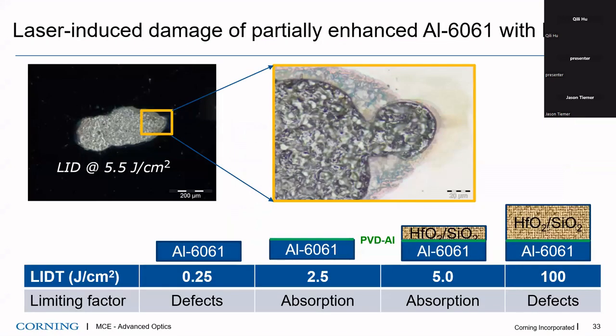But moving forward, how can we mitigate this, right? We develop the process. Basically, we use PVD aluminum to replace the aluminum alloy and to eliminate those defects. Based on that, we can expect, for the aluminum alloy itself, the laser-induced damage threshold we measured is a quarter joule per square centimeter. And if we apply our surface modification, we can increase the damage threshold by 10x.